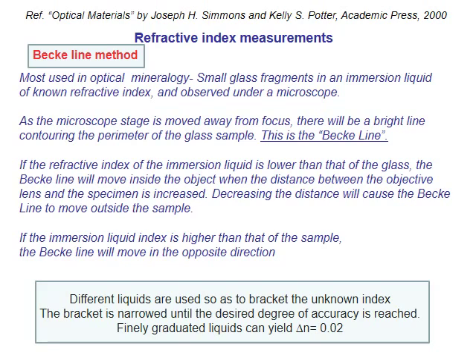If the refractive index of the immersion liquid is lower than that of the glass, the Becke line will move inside the object when the distance between the objective lens and the specimen is increased. Decreasing the distance will cause the Becke line to move outside the sample. If the immersion liquid index is higher than that of the sample, the Becke line will move in the opposite direction. Different liquids are used so as to bracket the unknown index. The bracket is narrowed until the desired degree of accuracy is reached.